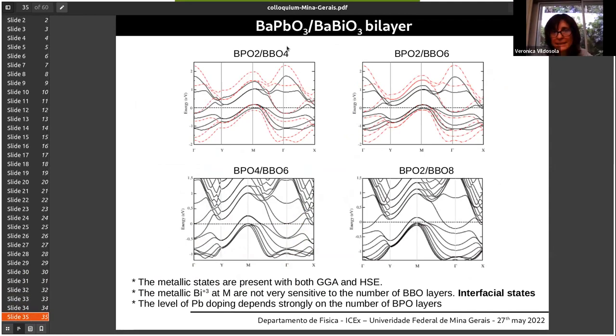We change the thickness of the BPO, and we haven't calculated the charge transfer quantitatively, but you can observe that when you have only two layers of BPO, the doping is much less than when you have four. Right. And this induces a larger hole doping in the bismuth 3 plus, which is in the other band. And the other bands, which are further away from the surface, are insulating. Right. And can you connect this transfer with the TC, given that you have calculated the electron-phonon coupling?